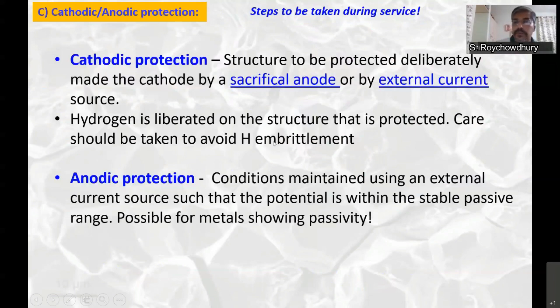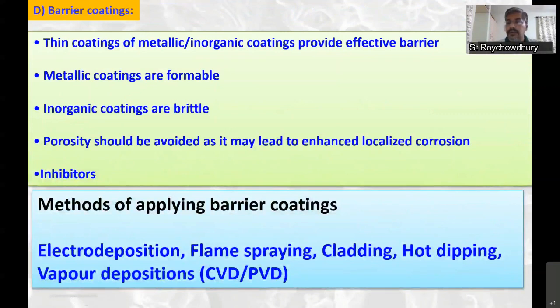So you can prevent uniform corrosion, one form of corrosion, but you can end up with a different form of corrosion like hydrogen embrittlement. Another form of protection is anodic protection. This is only valid for metals which passivate. So we maintain those environmental conditions such that you are within the region where the passive film is stable, and that gives a very low corrosion rate, even though it's anodic in nature. The metal is anodic.